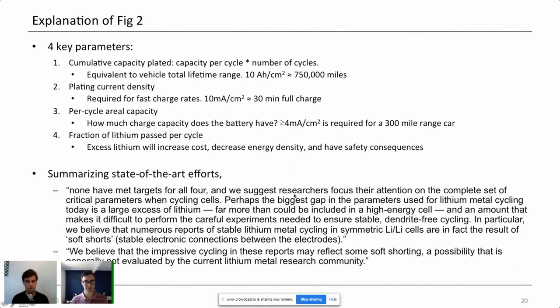And so they're neglecting some of the trade-offs that I mentioned earlier that are intrinsic in battery development. They say perhaps the biggest gap in parameters used for lithium metal cycling is the large excess lithium, far more than could be included in a high energy cell, and an amount that makes it difficult to perform careful experiments needed to ensure stable dendrite-free cycling. So they say, in particular, we believe that numerous reports of stable lithium metal cycling in symmetric lithium-lithium cells are actually the result of soft shorts. So let me explain what that means.